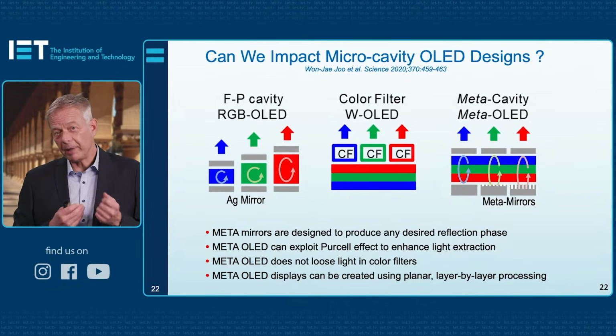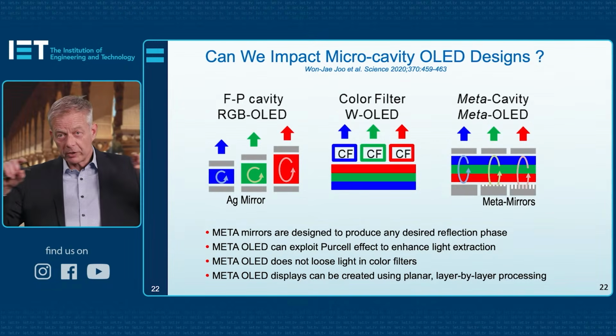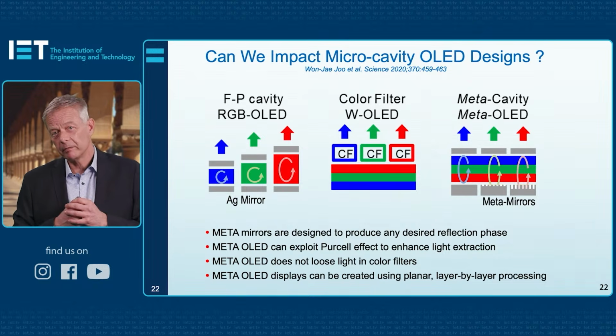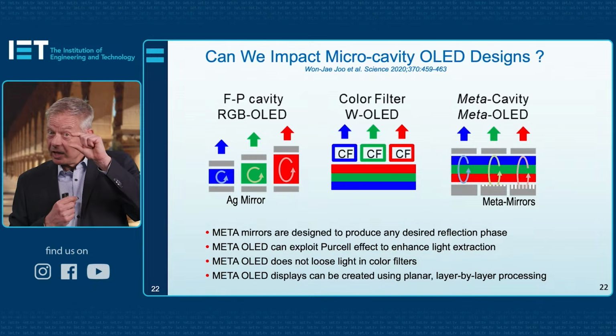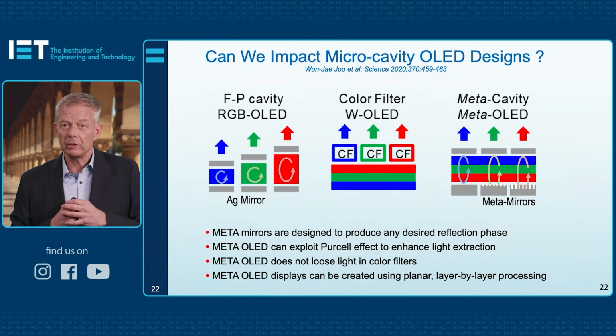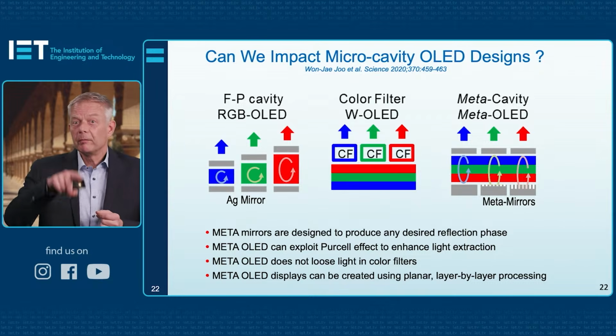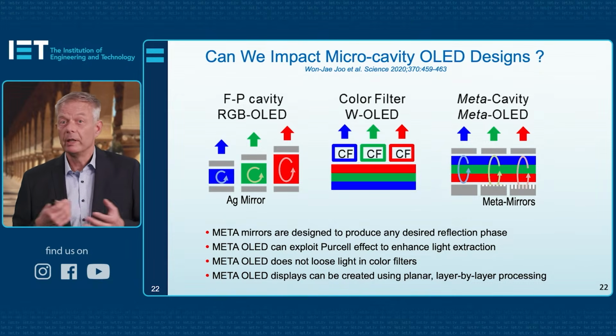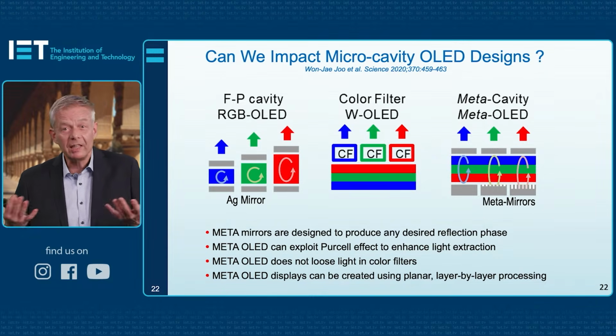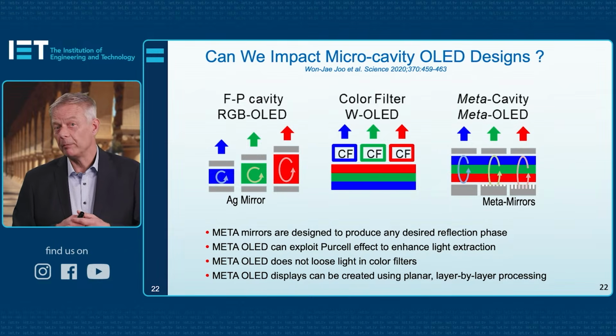And there on the right, we got back to these cavities, where now we could deposit continuous films of red, green, and blue emitters. But by having the same mirror spacings, but going to meta mirrors, we could manipulate the reflection phase and actually allow a resonant pathway to be set up for all the different mirror conditions, just by manipulating the reflection phase in different ways by having tiny little bit different pillars on different meta mirrors. So here, no light is lost due to absorption, and we could keep on continuing the scaling of these displays to smaller and smaller sizes of pixels or higher resolution.